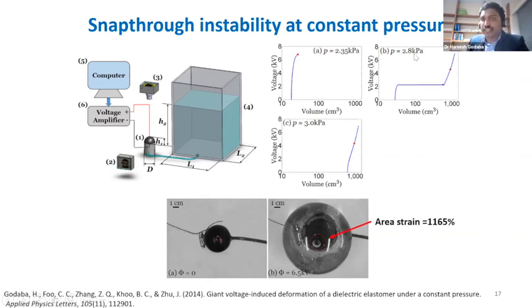But at an intermediate pressure, which is at the verge of this instability, if you keep the initial pressure close to the snap through pressure, then we can apply very small voltage, and that can trigger this snap through, which can help us achieve a very large volume change. So this is snap through instability at constant pressure by controlling the initial pressure. And once we saw this, we realized we can have this actuator that's coupled with fluid, and we can also achieve large volume change by triggering this snap through.